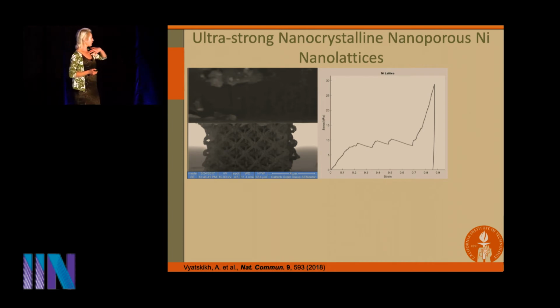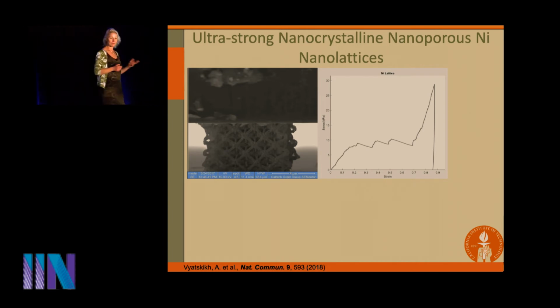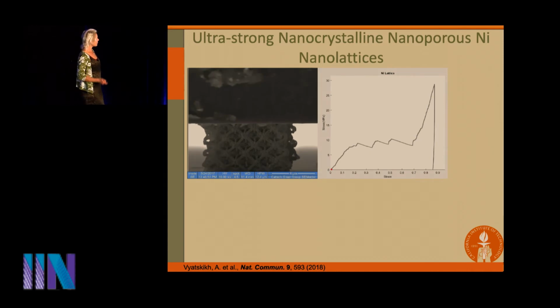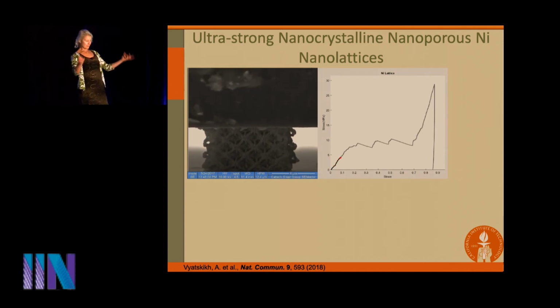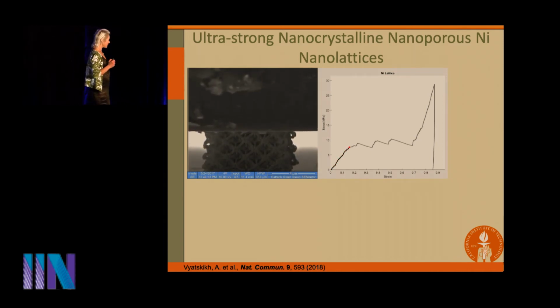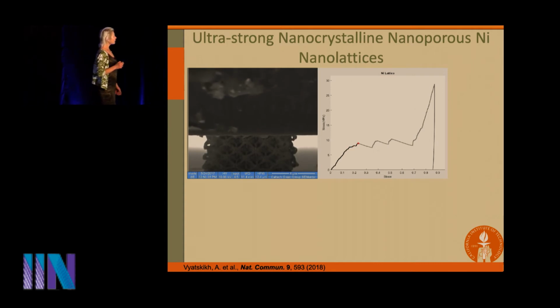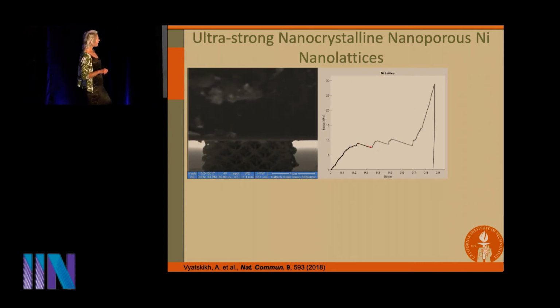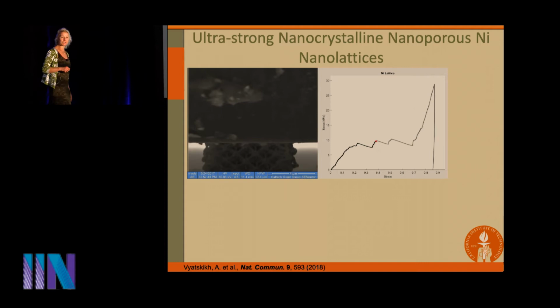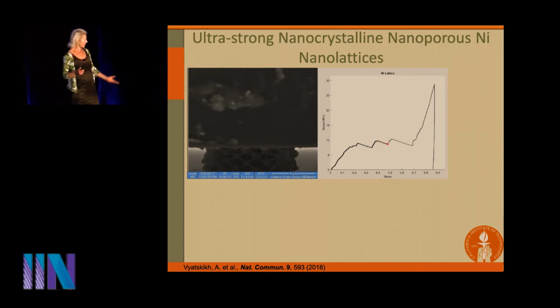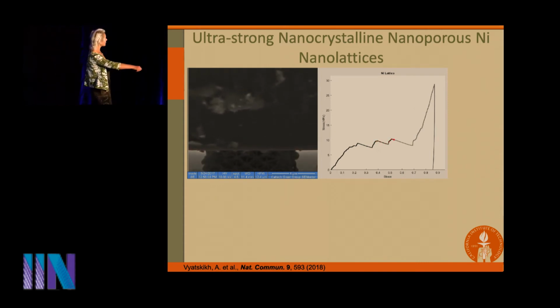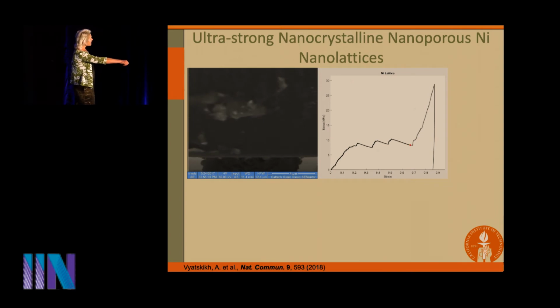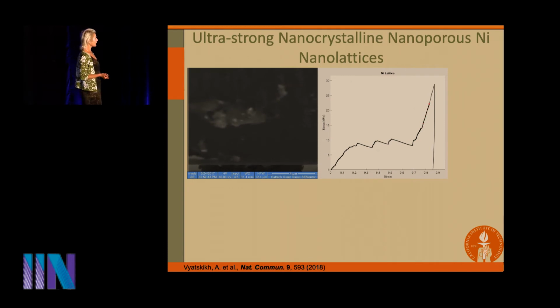So we're pretty good at measuring mechanical properties, so that's what we decided to do. So here's our nano-architected nickel, entirely made out of nickel, nanoporous, additively manufactured. And so we're compressing it and we're looking at the strength. The porosity here is about 30%, so it's not super lightweight, but it's still nanoporous. So we're looking at the stresses here. Well, they're about 15 MPa, and then once we've fully densified it, of course, it shoots up. So it deforms just like we would expect it to deform.